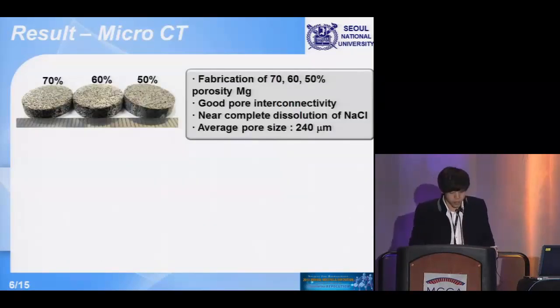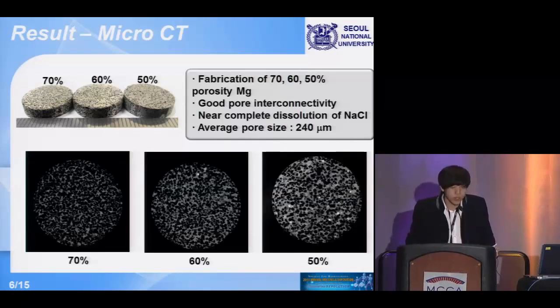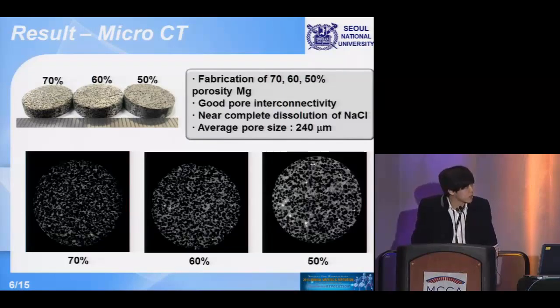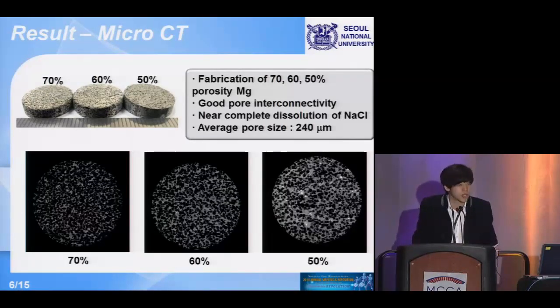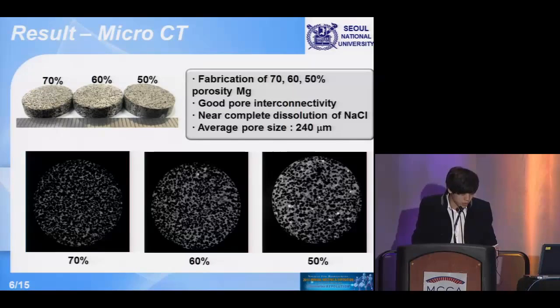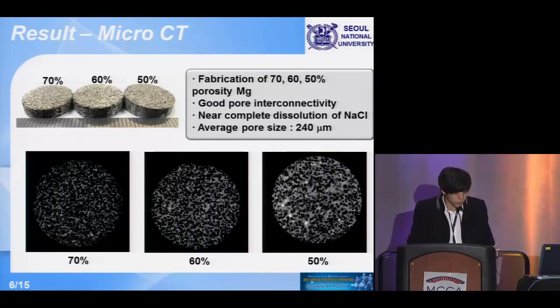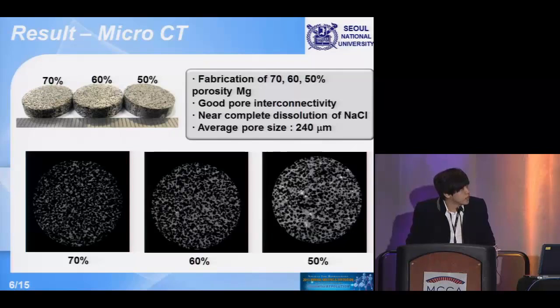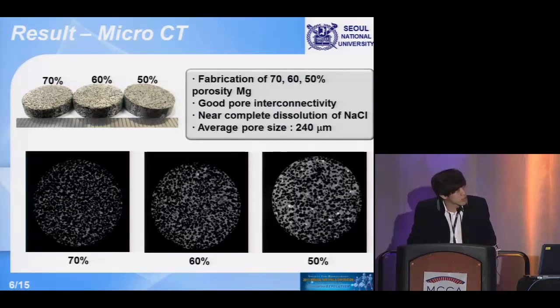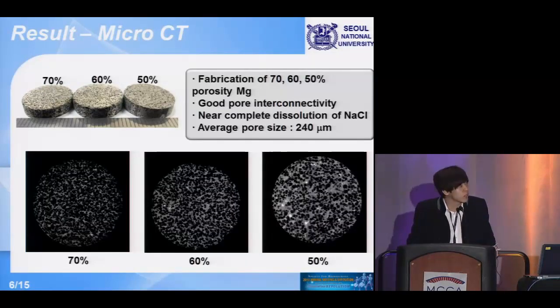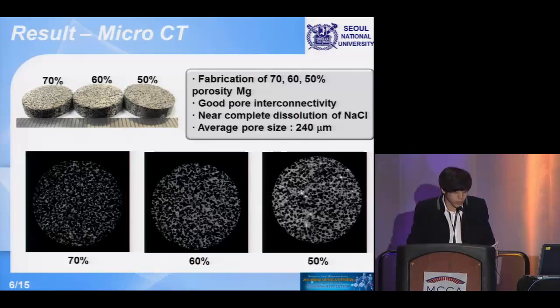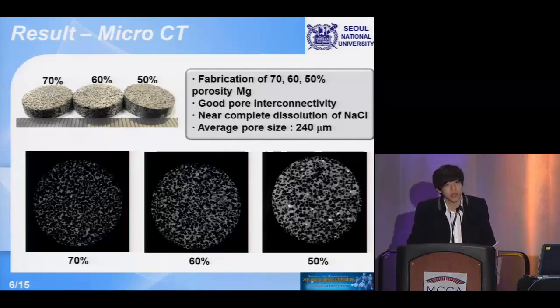These are the porous magnesium with different porosities, 70, 60, and 50%, made by changing the volume ratio of the sodium chloride. And this is the micro-CT result of them. As you can see from the micro-CT, there is very good pore interconnectivity and almost complete dissolution of the sodium chloride. The average pore size of the porous magnesiums was almost 240 micrometers, and you can change the pore size by using different sizes of sodium chloride.